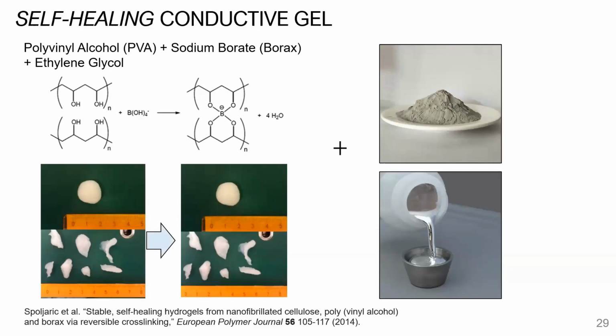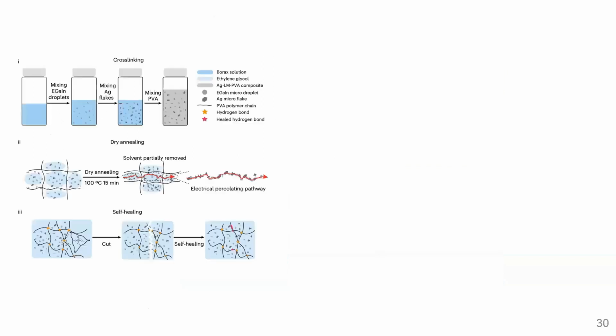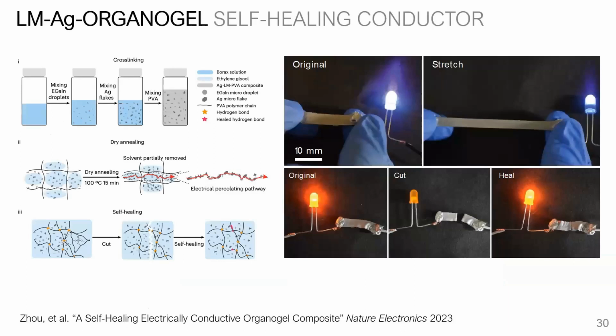So I showed you before that silver alone is good for achieving high electrical conductivity. But if we want these to be self-healing, we actually need the liquid metal in there. So when you sever the material and bring it back in contact, the liquid metal can help aid in wetting those silver flakes back together and restoring those percolating networks. So that's what you're seeing here.